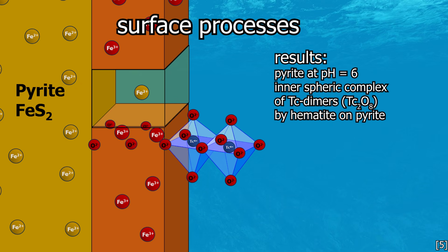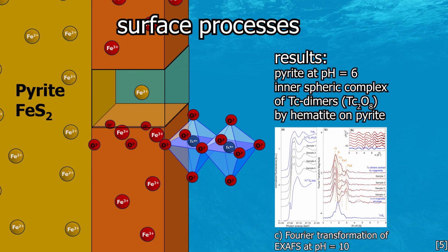In other words, there is a Tc2O8 unit that shares 2 oxygen atoms with the iron oxide. This is essentially an edge bond with the hematite. That was demonstrated using XAS, and this type of immobilization is very strong. Further interaction via OH groups is of course always possible.